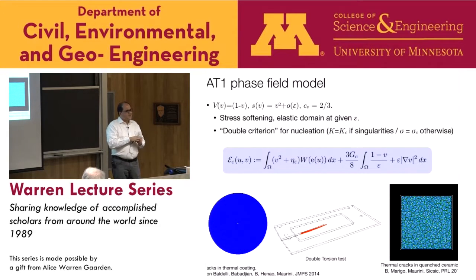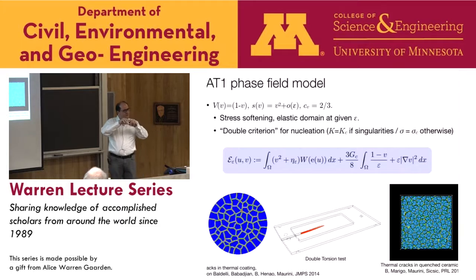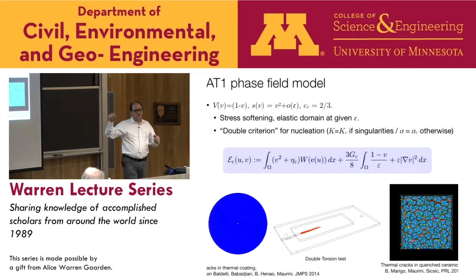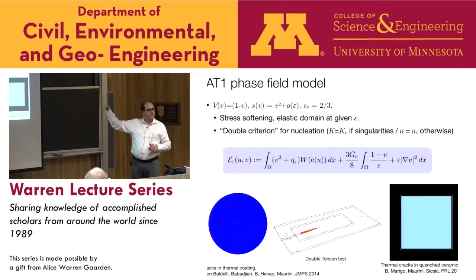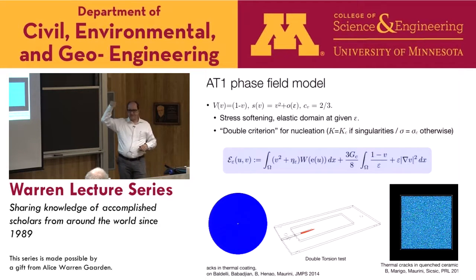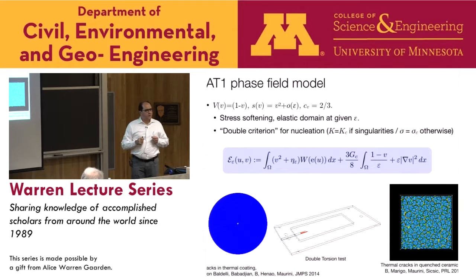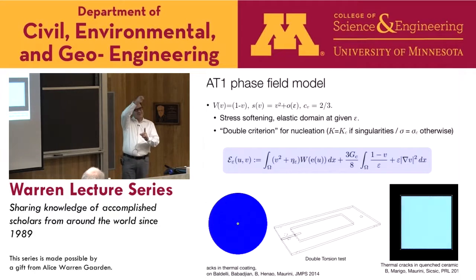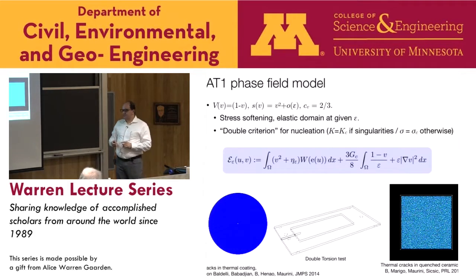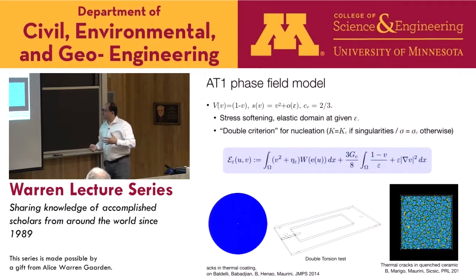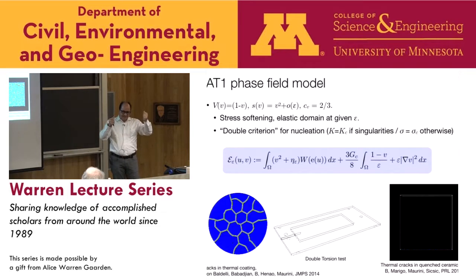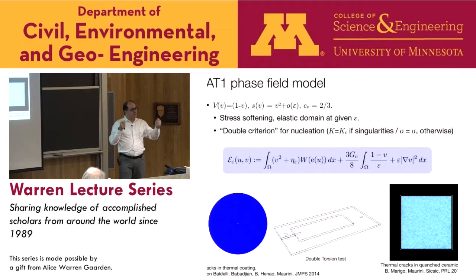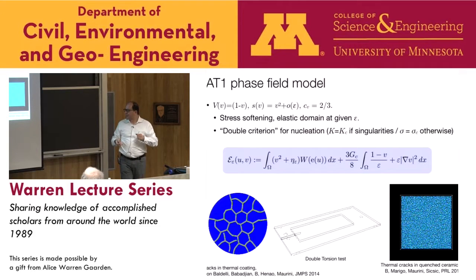The double torsion test is a wickedly smart way to compute the fracture toughness of a thin sample. The nice part is that you don't need to track the crack location. You can get the toughness just from the sigma-epsilon curve. It just has one flaw: in the lab it never works. On paper you have one nice crack that goes straight through the center of the domain, but if you do your experiment, you always see a crack that curves and jumps to the side of the sample. So what we did is try to understand what the crack path is sensitive to, whether it's the loading, the geometry, and so on.